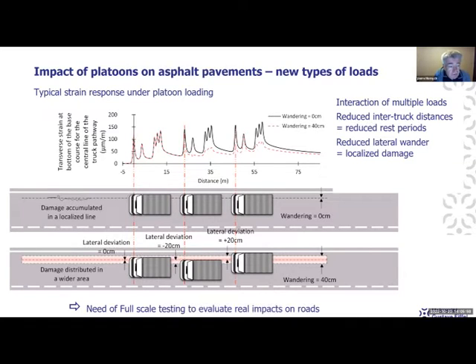So if you look at the strains produced by a platoon, you can see here an example. The strains are different from what you get under a single vehicle because you have several very closely spaced trucks. And the effect is that you have an increase of strains under the second and third vehicle due to the viscoelastic behavior of the pavement. And if there is also no control of the lateral position, you have a reduced lateral wandering with the platoon. And so you also localize the damage on the pavement.